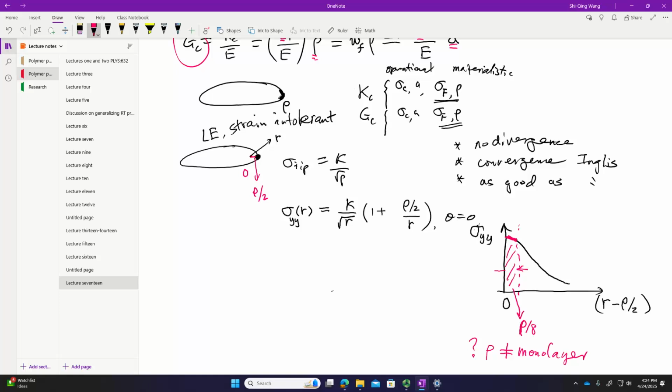And you now realize what you have been doing. You are preparing a crack like this with a tip. Can you control how sharp that tip is? Yes and no. That sharpness of the tip is up to the material to respond to how you are cutting it, how you are introducing it. So there is the possibility that whatever crack you introduced in your PMMA is such that rho could be, who knows?